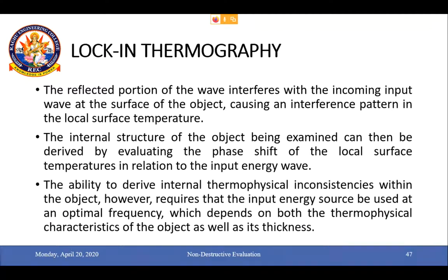The ability to derive internal thermophysical inconsistencies within the object, however, requires that the input energy source be used at an optimal frequency, which depends on both the thermophysical characteristics of the object as well as its thickness. So obviously, we have to set up optimal frequency levels, which depend upon the thermophysical characteristics of the object as well as its thickness. Without setting up an optimal frequency, we are not going to get a good result.